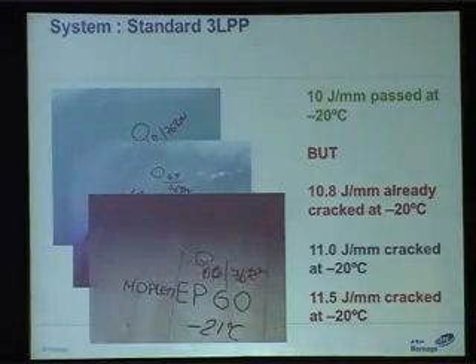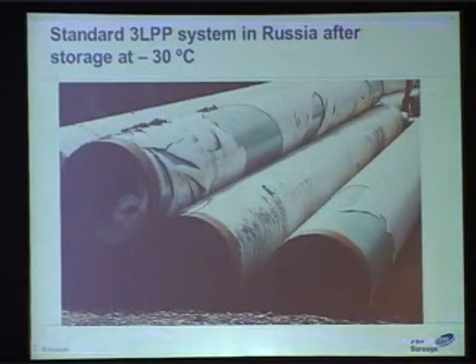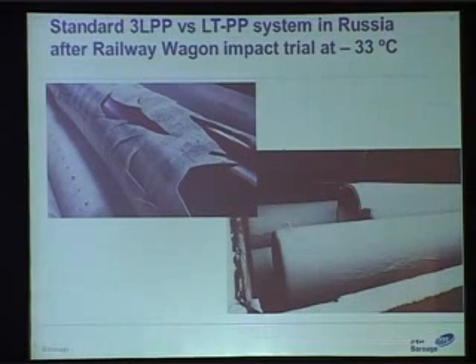The standard PP fell between 10.8 to 11.5 joule under the same conditions. These were the conditions of standard polypropylene in Russia after storage at minus 30 degrees centigrade. In Russia, they also do a special test called wagon impact test, where the coated pipes are stacked in a wagon which at a certain speed is made to collide with a static resistance. The standard PP completely cracked, and it was mostly on the floor of the wagon after the impact test at minus 33 degrees centigrade, whereas the low temperature PP system successfully survived it.